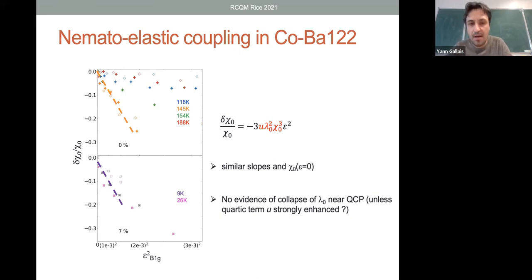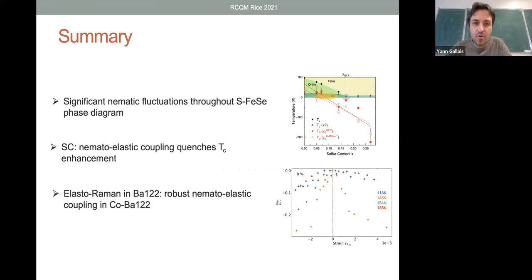Okay, let me finish with this. What I showed you is that there are significant nematic fluctuations throughout the sulfur doped iron selenide phase diagram. I think the key take-home message is that coupling to the lattice is important, and it's probably affecting the TC enhancement at the nematic QCP of the system. And I showed you that elasto-Raman measurements on barium 122 seem to indicate that there is still robust nematoelastic coupling down to the QCP, at least in cobalt barium 122. And I thank you very much for your attention.